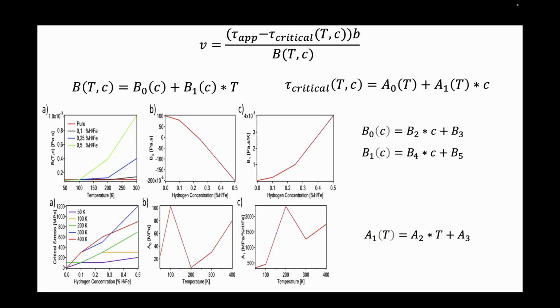So we have the drag coefficient as a function of both temperature and concentration. Once you plot this with respect to temperature, we get more or less linear lines, so we put a linear line equation, y equals mx plus n. Here, B0, the constant, is also a function of C. We don't know if it's linear or polynomial, but it's a function of C. And also B1 is a function of C plus the temperature. So this is just the equation of a line. Then we plot B0 as a function of C, and we saw it's a line, so it's just B2C. And once you plot B1 as a function of concentration, again a line equation, B4C plus B5.